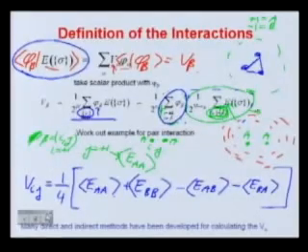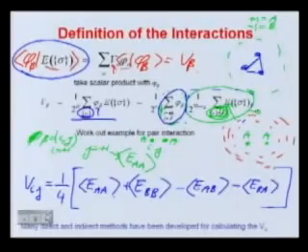If your system is symmetric, if I and J are equivalent, then these are the same. If you have translational symmetry between I and J, then you'll get something like -2 EAB. And those of you who've seen regular solution thermodynamics may recognize this as an effective prefactor in the enthalpy of mixing. You'll get something like the AA interaction plus the BB interaction minus 2 times the AB interaction.